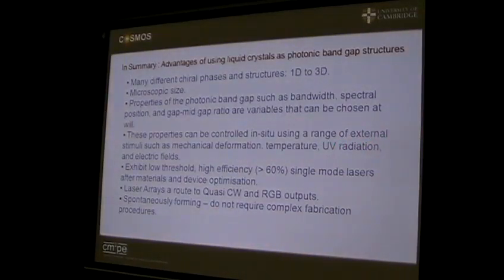And I think what's important is you can pick up on the technology of liquid crystal devices to make very efficient tuning. Liquid crystal lasers, you can make elastomers, you can mechanically deform. I showed you temperature. If you use the azo bimesogens, you can actually tune the order parameter in your system by flipping the azo dye. And you can tune your system. There are papers in the literature tuning the system with UV. We have done that work, but we don't push that work too hard, because of the relaxation time.